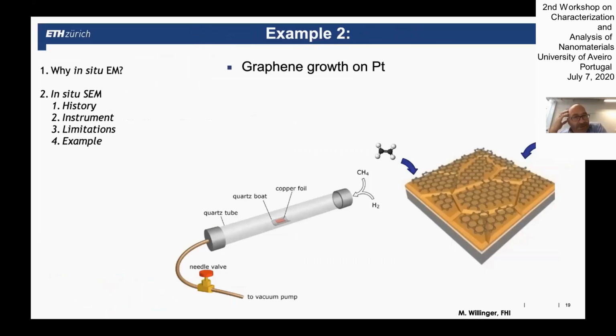Graphene was already discussed today during some presentations, and I want to show this because I'm absolutely fascinated by the high sensitivity of the scanning electron microscope. It has extreme surface sensitivity. We were studying graphene growth, and usually you grow graphene by chemical vapor deposition on some metal catalyst. Normally people have a quartz tube, heat it up to about 1000 degrees, and have a catalyst, often copper foil, and then they introduce a hydrocarbon hydrogen mixture.